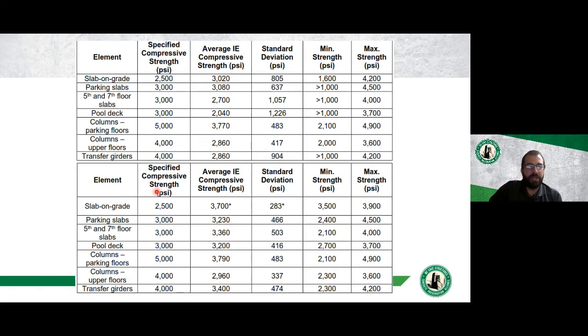But one thing we can do is look at the compressive strengths before and after removing the damage. And so the table on the top here is the average compressive strength of all of the data points. But then if we remove locations where we saw cracking or damage, so delamination, and we look just at what the compressive strength of the sound concrete is, we see that the average compressive strengths increase.